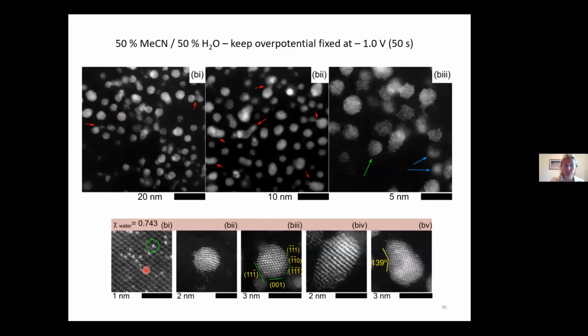Okay, if we go to 50-50, what we see is we're still seeing nanoparticles, and we still see in the background, we can see our single atoms, and this allows us to do atom counting. If we can get a single atom, we can do the intensity, but we're seeing a greater emergence of coalesced structures. So more of these nanoparticles are coming together to form coalescence. And we can start to look at these in higher resolution.